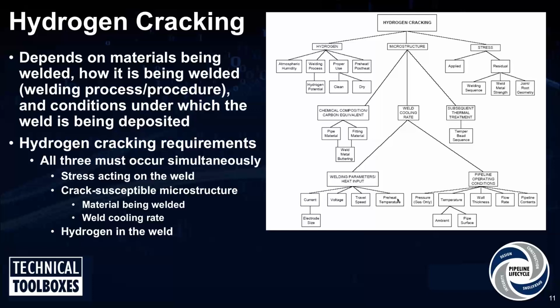Now, the hydrogen that we're worried about, it is atomic hydrogen. So how do we get atomic hydrogen in our weld? It comes mainly from the welding electrode coating. Again, going back to the low hydrogen and cellulosic electrodes. Low hydrogen obviously has low hydrogen content, and the cellulosic electrode has a dramatic amount of hydrogen in it. And the hydrogen that comes from the welding electrode gets dissolved or dissociated in the welding arc and gets absorbed by the weld pool. And as the welder travels, that weld pool solidifies. So your weld bead has a certain amount of the diffusible hydrogen or atomic hydrogen solidified in the weld bead upon the deposition of that weld.